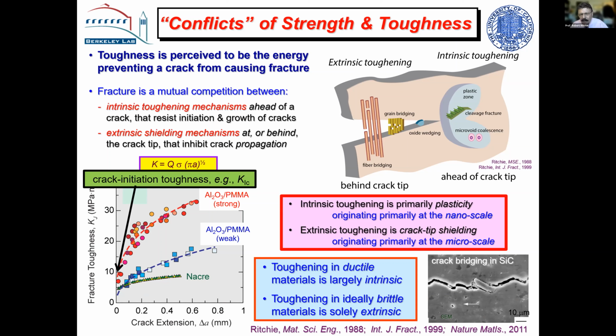But of course, if you stop there, you leave all this extra toughening associated with the stable growth of cracks. And this toughening is associated with the phenomenon behind the crack tip. Plasticity, if it's intrinsic toughening, or the toughening mechanisms themselves, if it's extrinsic toughening. And this is known as the crack growth toughness. And this is absolutely important from the perspective of damage tolerance. By the same token, you don't want a material like a piece of chalk that simply snaps when you break it. You want some ductility. That's basically a requirement for a structural material almost.